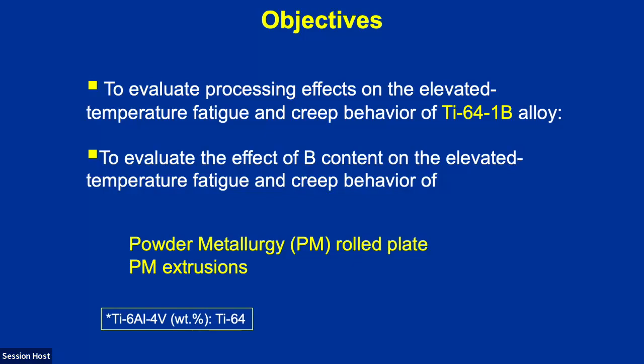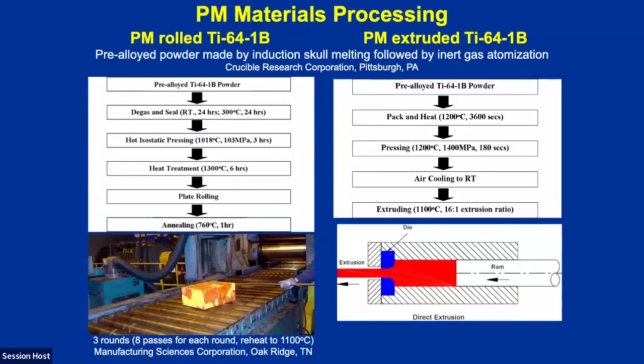We looked in particular at powder metallurgy rolled plate versus powder metallurgy extrusions, and we're going to compare those to cast material. Here on the left is powder metallurgy rolled Ti-64 with 1 boron, and on the right is powder metallurgy extruded Ti-64 with 1 boron, where the 1 boron is by weight percent.